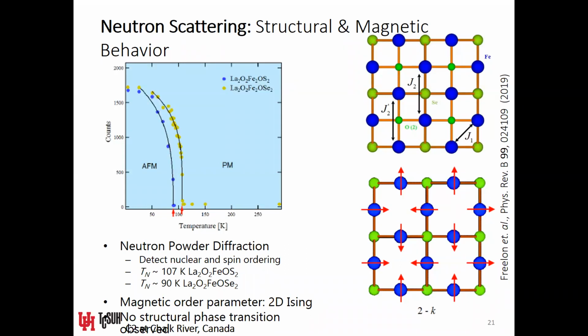The magnetic data that we took used neutron diffraction, and we wanted to map out or understand the onset of the antiferromagnetism in these materials. And we wanted to see whether or not the structure underwent a phase transition. So it turns out that these materials do not undergo a structural phase transition, but they do show 2D Ising model behavior as they make this magnetic phase transition from a paramagnetic phase at room temperature down to an antiferromagnetic phase at lower temperature.